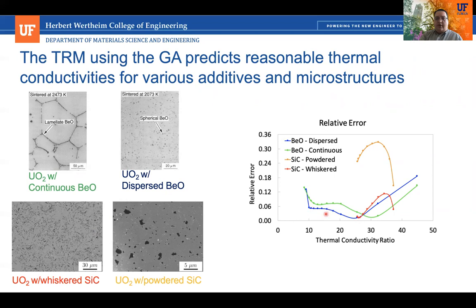And you can see the error for different ratios of the UO2 thermal conductivity and the thermal conductivity of the additive. And what we find is that the errors are fairly low, 15% or less in general, but they tend to increase some with this thermal conductivity ratio. And we also find that there's this one sort of outlier microstructure, the powdered silicon carbide, this one, which was worse, but still 35% error or less, but not nearly as good.